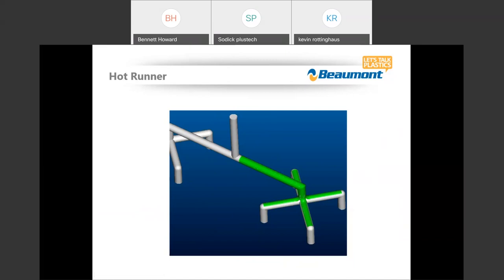Let's talk about stack tools for just a quick second. Stack tools, we have a really long sprue bar. So if you ever run a short shot on a stack mold, everybody knows that the A side of that stack mold, the split on the side nearest to the stationary side of the tool, that side actually always fills faster than the B side, if you will, the movable side of the tool. And that's because those laminates coming up to the intersection, I'll draw this out real quick. When we have that sprue bar coming in to our split between the halves, that annular ring is continuing and then coming up to this intersection and splitting non-uniformly towards the A half.